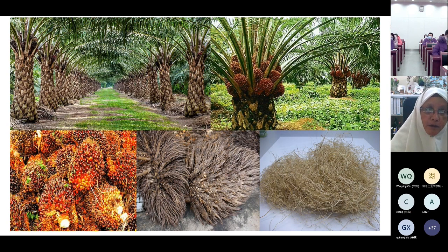And the fruits, once you remove the fruits, you're left with the empty fruit bunch. This empty fruit bunch, if you shred it, can give you quite a high proportion of fiber, about 20% to 30% good fiber. It has been utilized for pulp and paper, composite materials, for beddings, and also for landslides and so on and so forth. For palm oil itself, the fiber is about 100 million tons a year. If you really wanted to utilize it, only maybe 10 to 20% has been used, but not all, because it has to be processed immediately at the plant after the fruits have been removed from the empty fruit bunch.